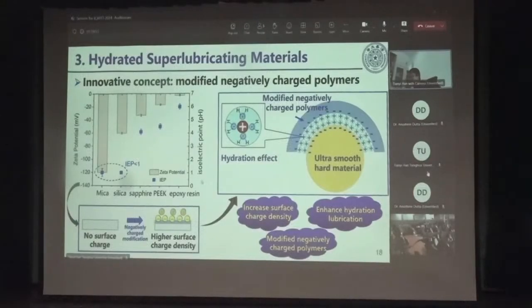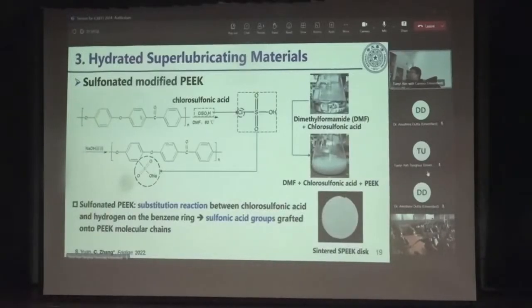Then we can get a surface with strong hydration effect. Let's see what happened based on this concept. We modified the PEEK powder by grafting the sodium sulfonate group. And then we sintered the modified PEEK powder into a disc for the tribo tester. This is the final modified PEEK disc. If we put this modified PEEK in water, we can expect the surface will release the sodium ions and become negatively charged. Let's see what happened.